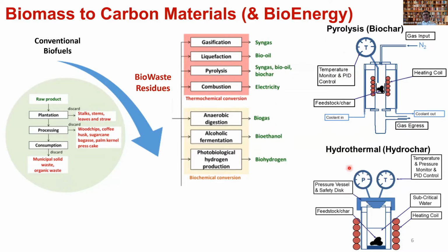So pyrolysis and hydrothermal carbon are two potent carbon materials. The way pyrolysis is done is that you take carbon feedstock and heat it to a higher temperature that could range anywhere from 400 degrees to 800 degrees Celsius under inert atmosphere. In that process you do thermochemical breakdown of that material. There are many different drivers, not only the temperature, but you can do fast pyrolysis or slow pyrolysis, and you can vary the rate of pyrolysis and so on. Everything makes a difference, and the starting feedstock also makes a big difference, as we'll see in some of the slides later on.